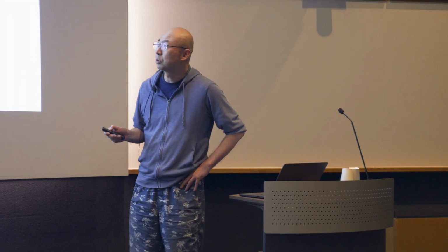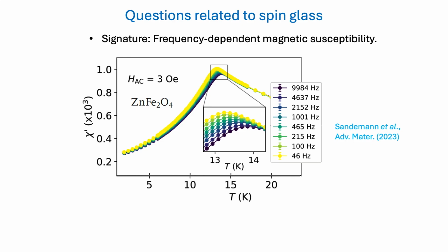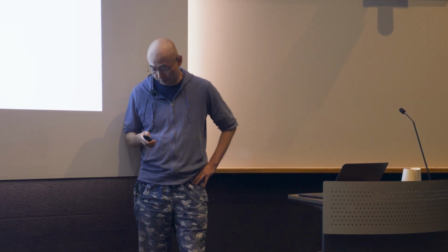Now we realize that there's still an unsolved problem in the previous case, which is that the system is a spin glass. It's said to be a spin glass, and you can see very clearly a frequency dependence in the susceptibility, even for the stoichiometric materials. The spin glass phase, as we mentioned before, was not resolved in the mathematical work. The mathematical work has its own rigor in the construction, and that's why it's recognized. However, there's no experimental connection to the real materials. In experiments, we haven't really established what the spin glass system is. There are a lot of signatures here and there, but lots of people will say it's just short-range spin clusters.